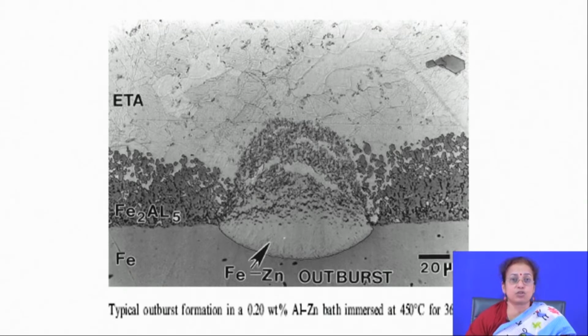If the time is very short, there is no problem; there is Fe2Al5 phase formation, and on top of that there is molten zinc with iron in solution. But if your time is quite long, then because of the large time available, there is molten metal diffusion through the intercolumnar porosities of the Fe2Al5 layer, and that molten zinc can go inside the iron through grain boundaries and form different types of intermetallics at the grain boundary regions. So, you will find that there is a local change in the concentration of zinc, as a result of which there is local formation of iron zinc intermetallics.